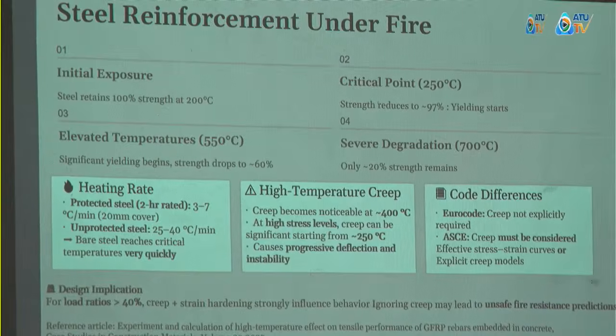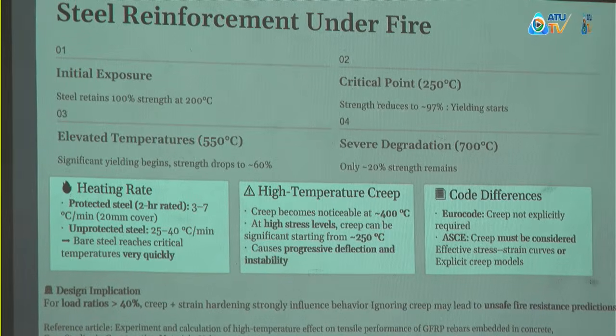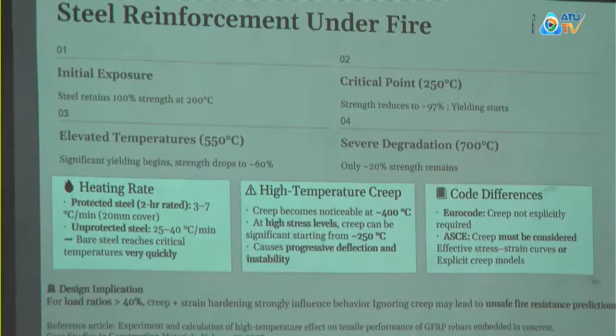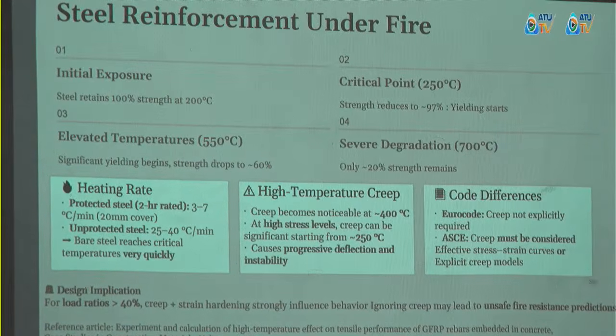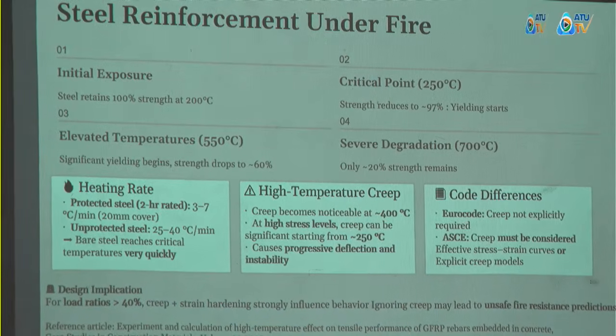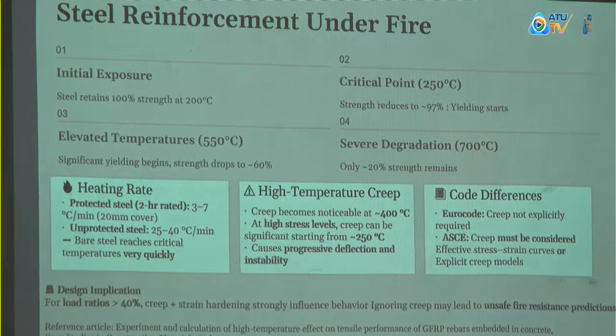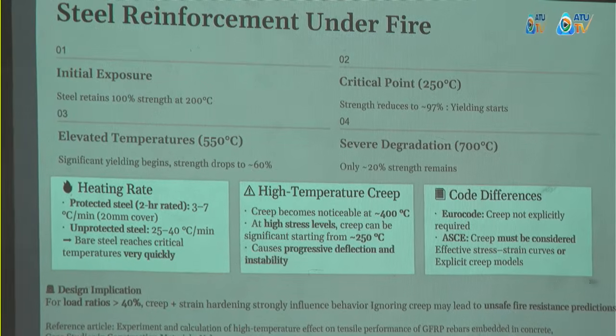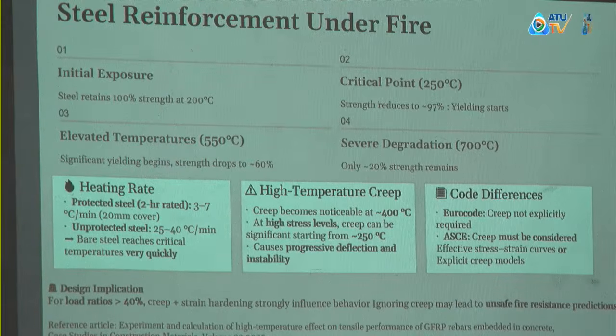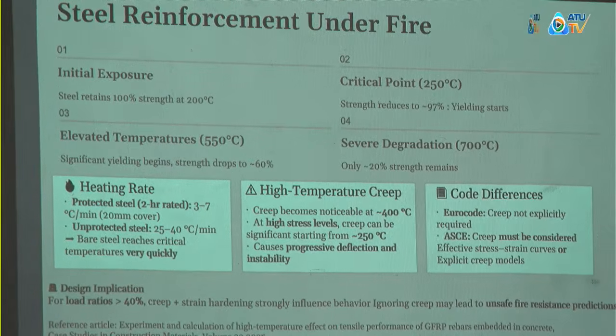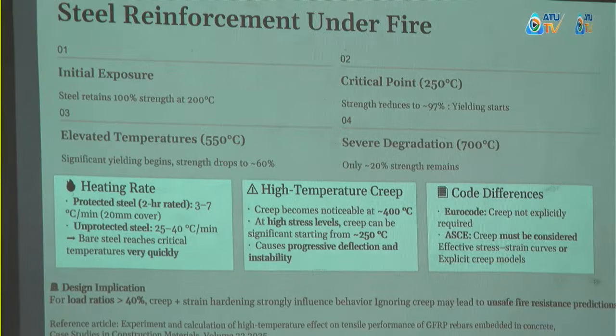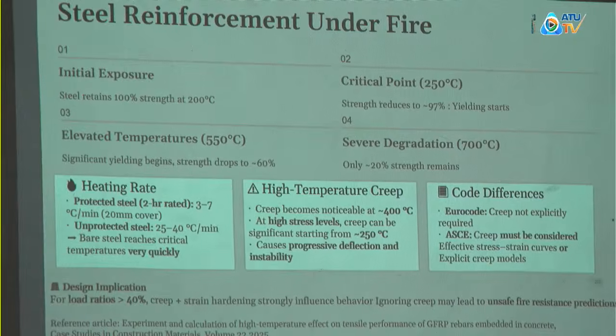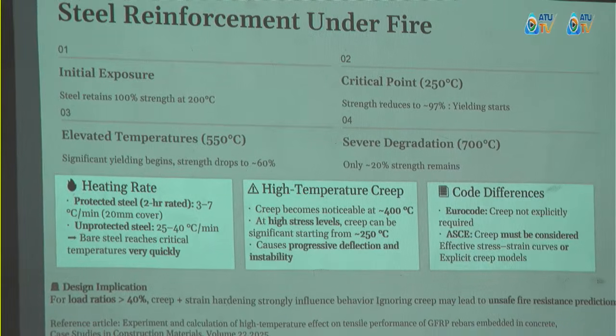And this is a test that I've done, and I have an article on fire, comparing the fire exposure of steel reinforcement to the Viva bar reinforcement, of which, as you can see, the steel behaves predictably under elevated temperatures, up to 200 degrees Celsius. And above 200 degrees Celsius, when we get past the point I mentioned earlier where concrete starts to fail and crack, at this stage the fire is exposed directly to the reinforcement.